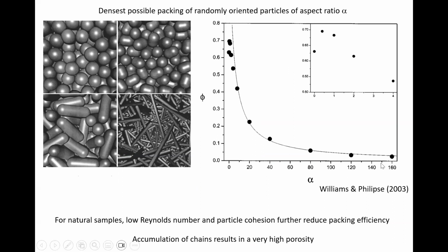So the best possible packing you could get as a function of shape. So here's your aspect ratio here. This is just a close-up of this zone here. And you can see that the porosity, well, this is the packing density, right? This is the inverse of porosity. It drops precipitously once you've got more than 4 or 5 grains, essentially forming a chain. So this is the best case scenario that we've got.